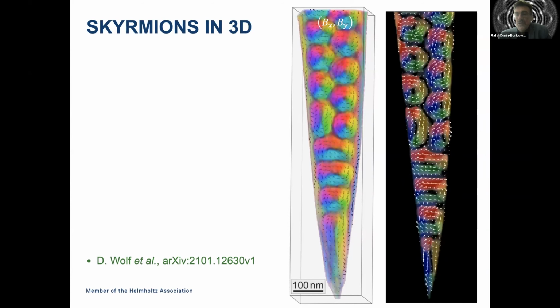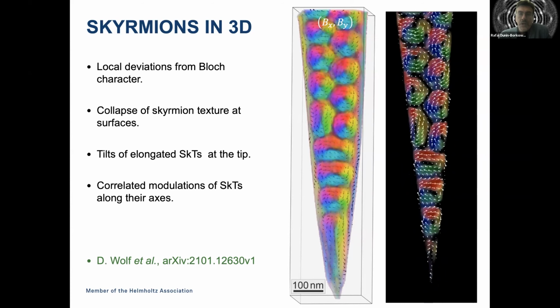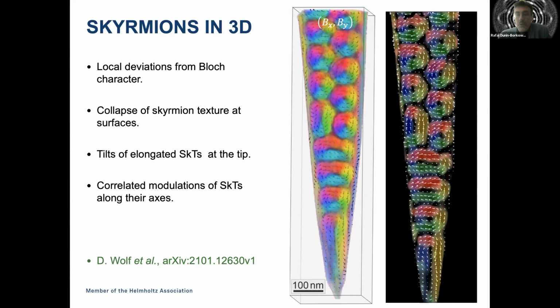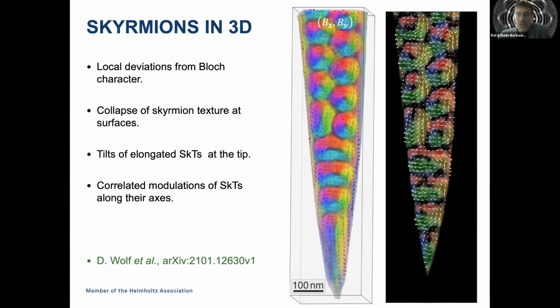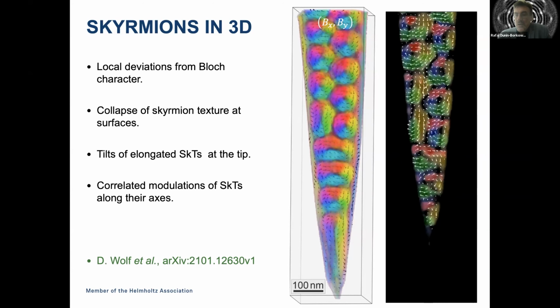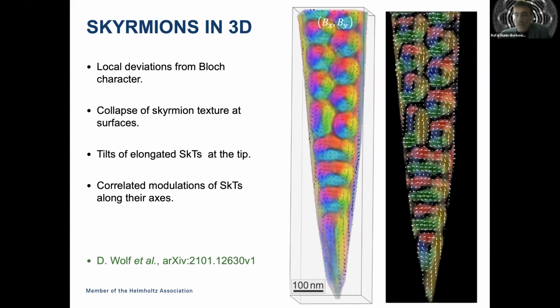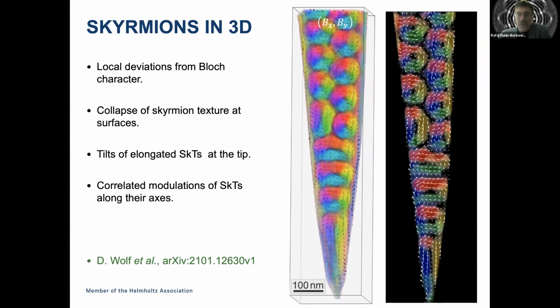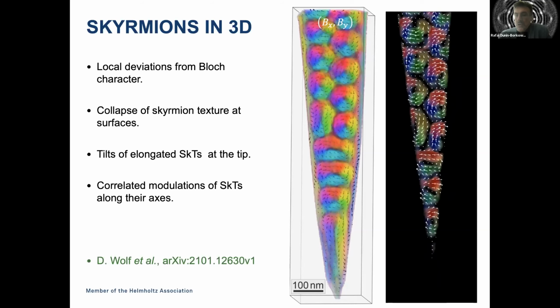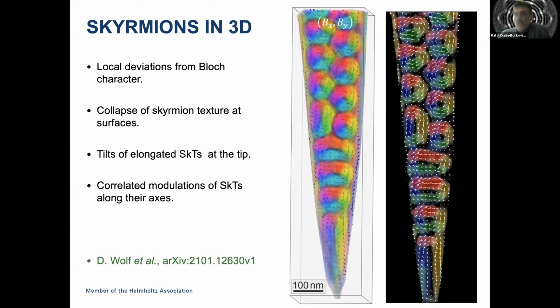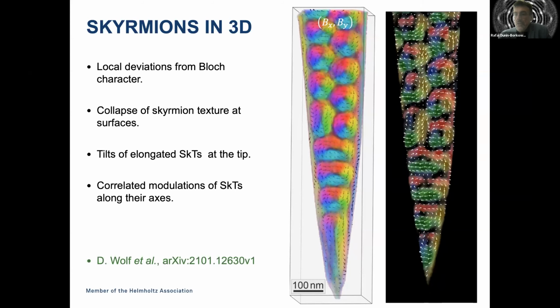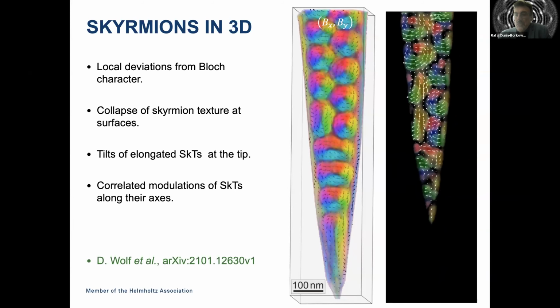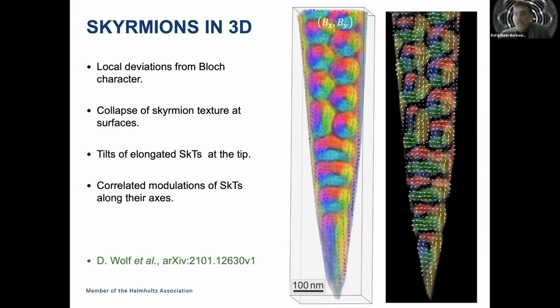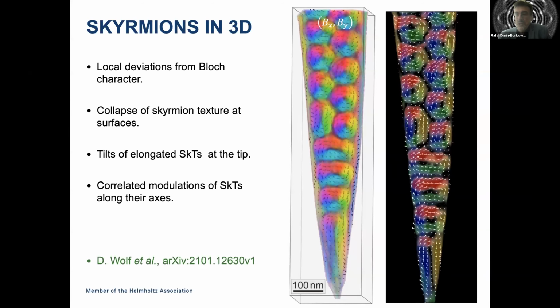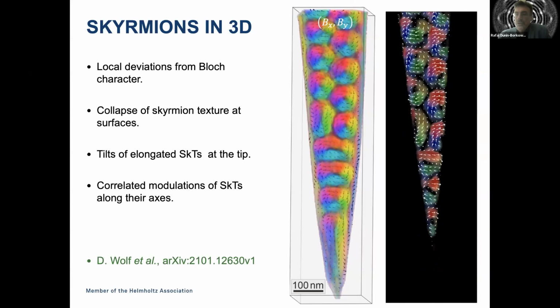What is very interesting from the three-dimensional reconstruction is that there are local deviations from Bloch-like character. Some of the skyrmions collapse at the surfaces of the sample. Some of the skyrmions are not parallel to the applied field direction. And there are some correlated modulations of the positions of the centers of the skyrmions from one skyrmion to the next. And all of this is impossible to see unless you can reconstruct the magnetic vector field in 3 dimensions. This is with nanometer spatial resolution. So this is a reconstruction of the magnetic field B.